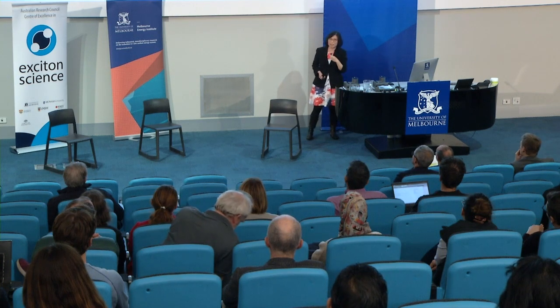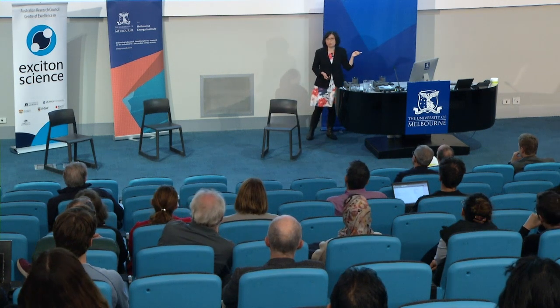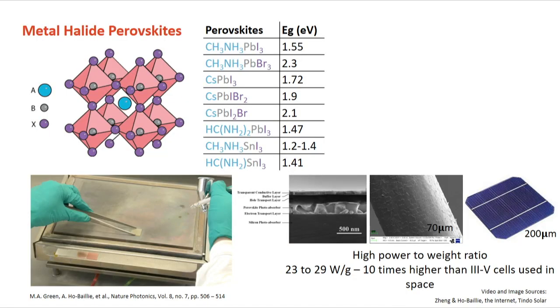So what is perovskite? Well, it's got a chemical formula of ABX3 and a crystal structure like that. The A site is an organic cation, and the B site is where the metal sits. It's got lead, germanium or tin, and then the X site is where the halide sits: the iodide, the chloride, and the bromide. And you can see Eg is the band gap. As you tune the composition of the material, you can change the band gap of the material. So that makes this material very versatile, whereas with silicon, it's only one band gap. You can't do much about it.